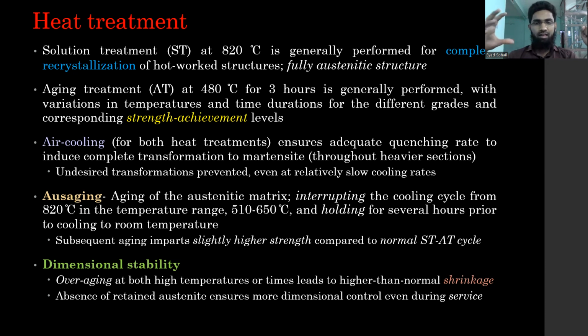Air cooling is sufficient. It ensures a sufficient cooling rate and doesn't need to be water cooled or water quenched or oil quenched, because it ensures an adequate quenching rate to achieve complete transformation to martensite throughout the heavier section, not just the thinner section. For sections having moderately high or higher thicknesses, air cooling is sufficient even there. Undesired transformations are prevented even at a relatively slow cooling. Even if the cooling rate is very slow, there is no undesired transformation. For example, austenite doesn't transform to bainite or pearlite or ferrite. It transforms to, say, martensite.